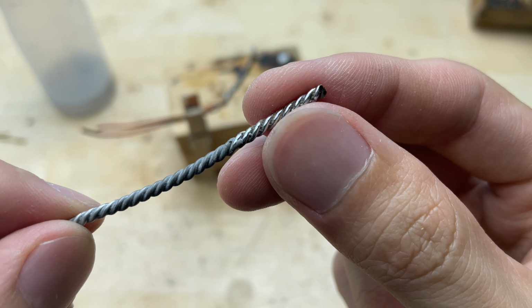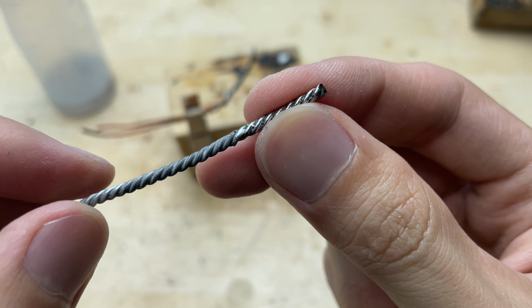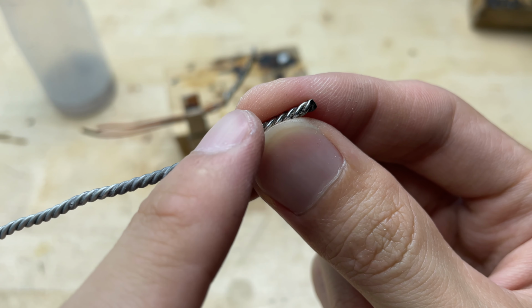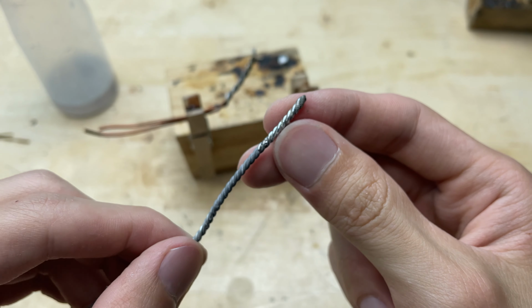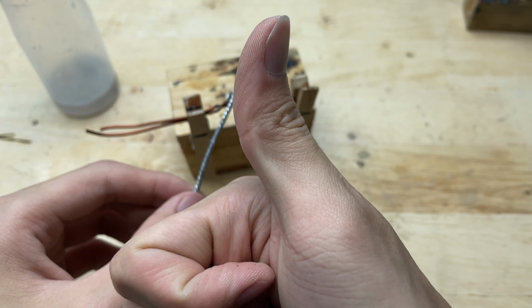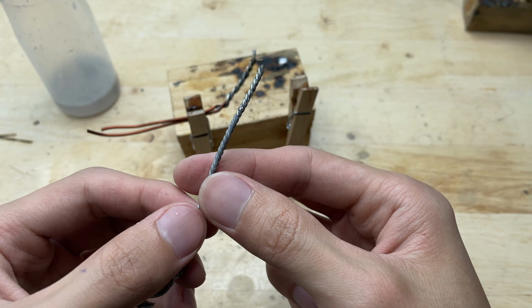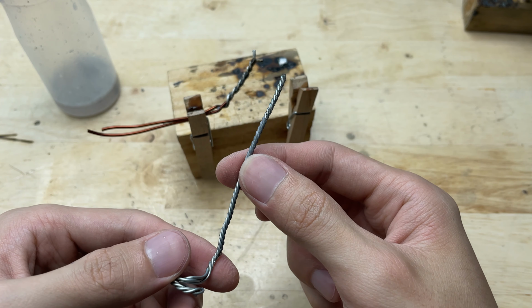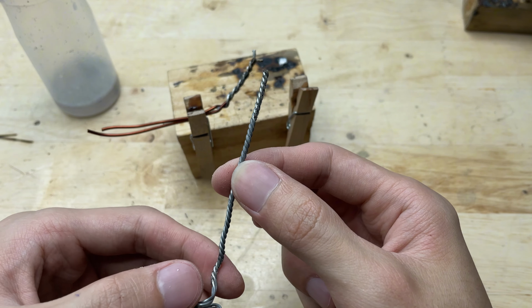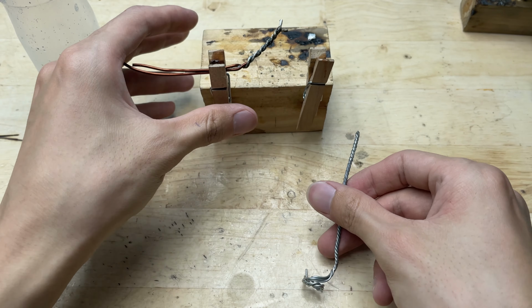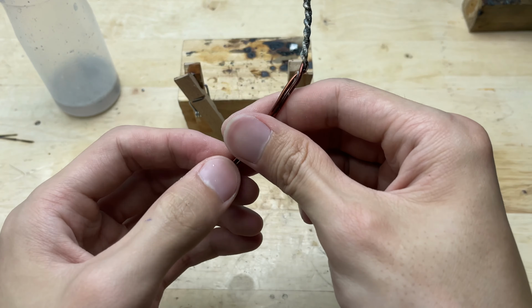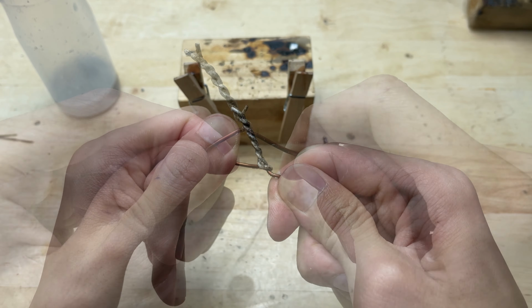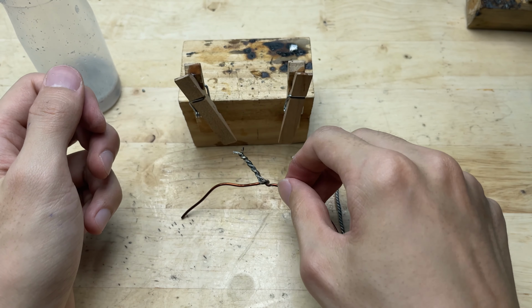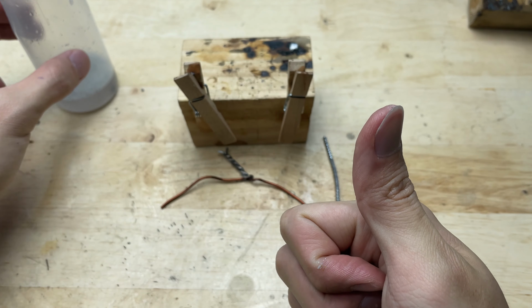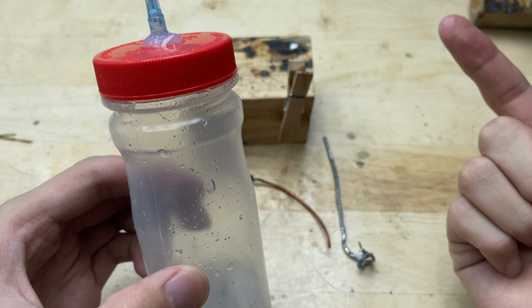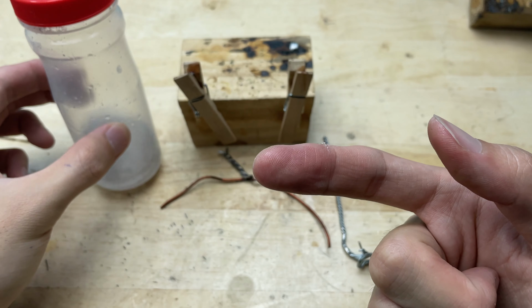Through this experiment, it's clear that the homemade solution works effectively as a flux substitute. It cleans the metal surfaces, removes oxidation, and significantly improves the adhesion of solder on both aluminum and steel, metals that are typically difficult to solder using conventional methods. The final solder joints are not only strong but also visually clean, smooth, and well-formed, demonstrating the importance of proper surface preparation. This simple and cost-effective approach delivers impressive results, making it a valuable technique for DIY projects or basic repair work.